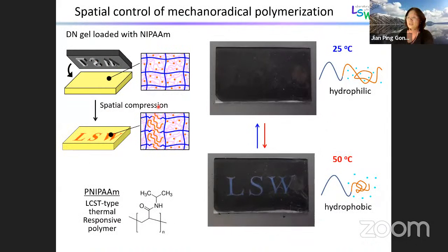So mechanically, this grafted chain will not strengthen the hydrogels. It probably can only induce phase separation locally, or change the surface property, or the hydrophilicity and hydrophobicity, something like this. But mechanically, without additional interaction, this will not change the mechanical properties.